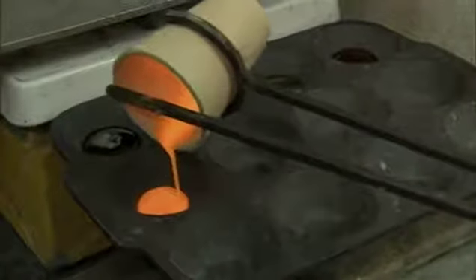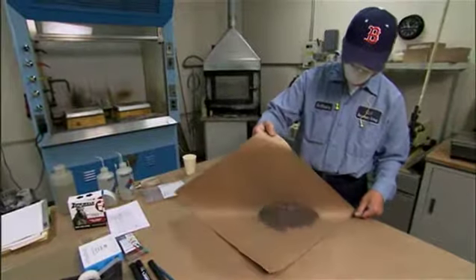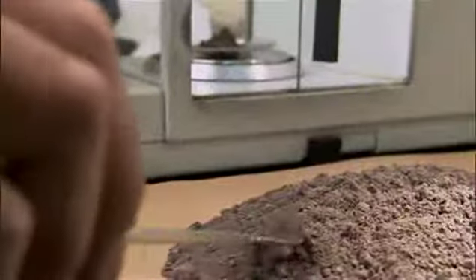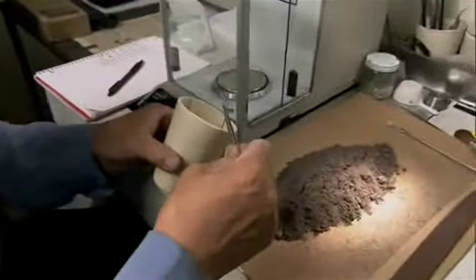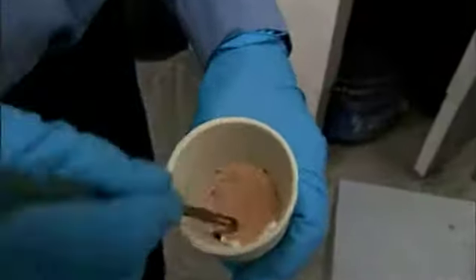If it has gold and silver present, then we would use a traditional fire assay method to determine the percentage of gold and silver within that powder. A sample of the powder is taken to the lab where it is rolled by hand to further ensure it's evenly blended. The powder sample is divided into 3-gram portions and mixed with the flux in a crucible. The flux is a standard mixture of lead oxide, soda ash, borax, silica, some flour.